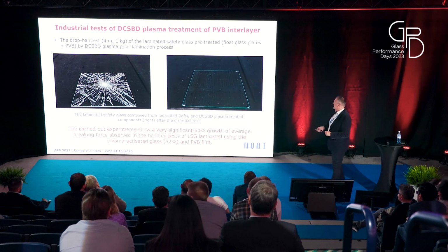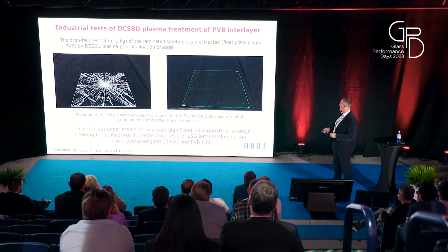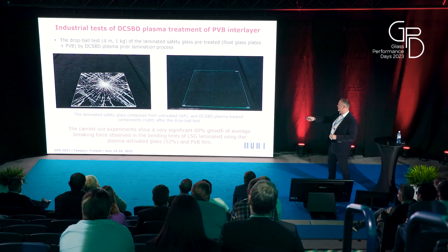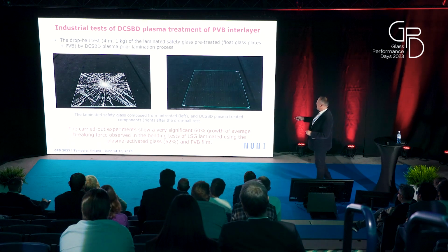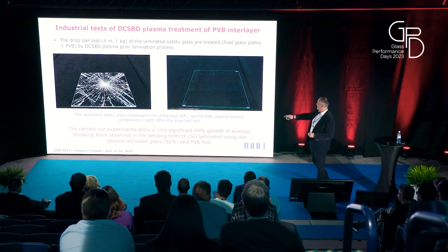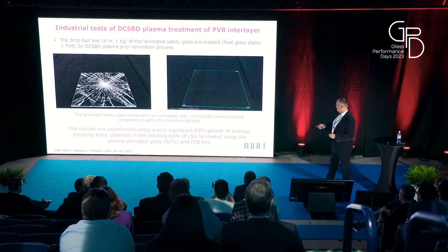Using a bending test, we verified a significant 60% growth of average breaking force. When only the glass was plasma activated, the increase was 52%.